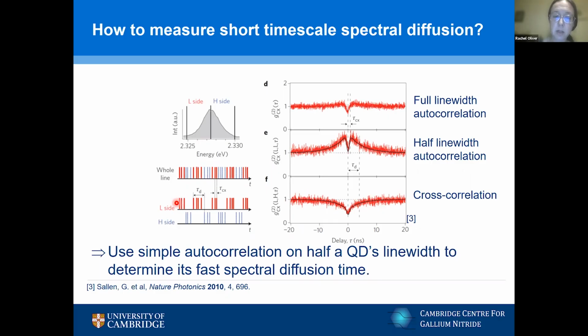So we get a bunch of photons emitted on the low energy side, and then nothing at all if we're only monitoring the low energy side of the peak. And if we do, therefore, a half line width autocorrelation experiment, we pick up that bunching, that tendency of the photons to arrive in bunches, as a rise in our correlation function. And the timescale of that drop-off gives us an idea of the timescale on which we're stable on one side or the other, the low energy or the high energy side. So using this approach, we can work out an estimate of how fast this fast timescale diffusion occurs.